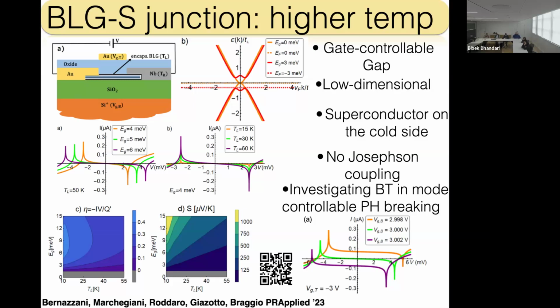Also here, we were able to demonstrate that using this gate, you can shift the chemical potential, because this is essentially a semiconductor. Instead, in a normal metal, no. In a normal metal, when you change the density of the electrons, you change the chemical potential and the gap opens around it. But for a semiconductor, by changing the gating, you can move the chemical potential in the band. Okay, this is the big difference.